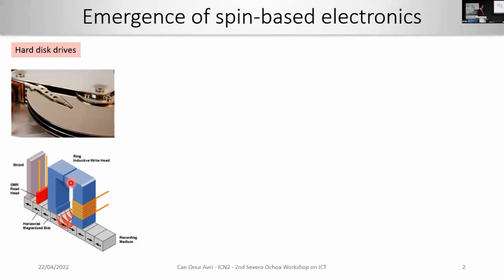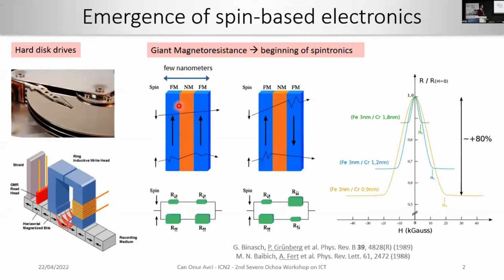The miniaturization of such a scheme was enabled by the invention of the giant magnetoresistance. The giant magnetoresistance is a magnetoresistive phenomenon occurring in magnetic multilayers due to the spin-dependent scattering of charge carriers, the electrons in this specific case, at the interface and bulk of the ferromagnets. Here you can make a few-nanometer film consisting of two ferromagnets separated by a non-magnetic material. Depending on the relative orientation of the ferromagnetic materials' magnetization, you can have either a low resistance state or a high resistance state. The change in the resistance between these two states is actually giant.